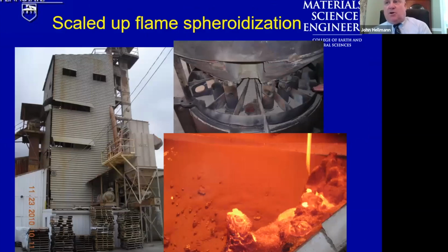So we scaled up. To go from the teaspoonfuls per day or week to tonnage quantities per hour required industrial manufacturing capacity, which we were able to access through a collaboration with ANH Refractories, now Harbison-Walker Refractories again. This is a flame spheroidization tower that was developed back in the 60s by ANH for manufacturing expanded kaolin-based products for insulating refractory manufacturing. Well, we used it to go ahead and do a flame spheroidization drop tower approach, much like you would make lead shot for shotguns, in which we granulated the metabasalt powders using pan mixing processes to form large granules on the order of 1 millimeter or so in size, and then dropping them through the hopper at the top of the tower.